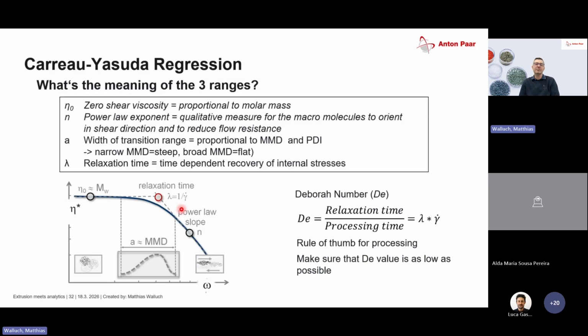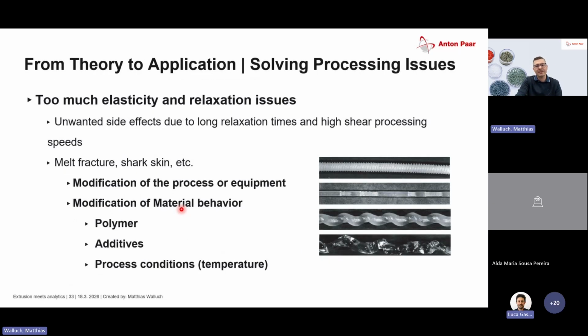The relaxation time is important because, based on the relaxation time, you can calculate if a process works or not, because there is something called the Deborah number, which sets a relationship between relaxation time and processing time. And you have to try to keep this as low as possible to be in a good process window. Why is that, or what happens? We can see here some effects that come from a too high Deborah number. So we have shark skin, we have melt fracture, and all these kinds of effects. This would not be acceptable as a product in the end because the material surface doesn't look like it should. And now the question is how to prevent this.